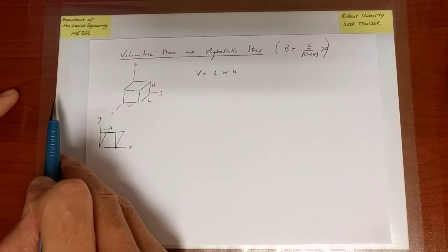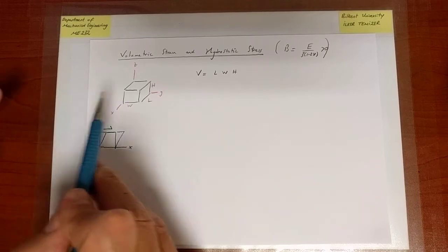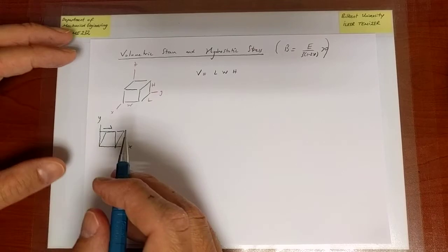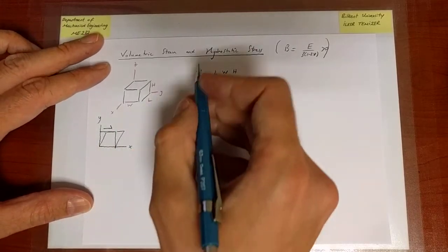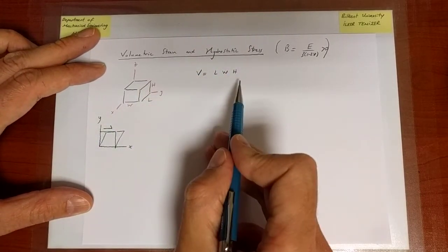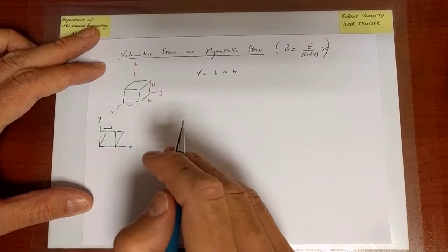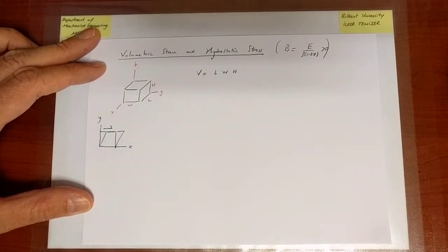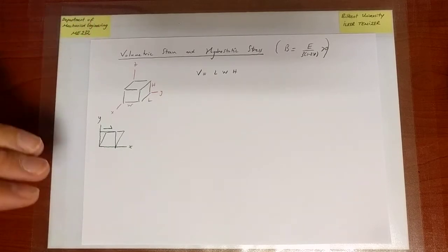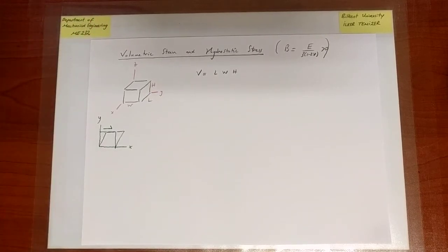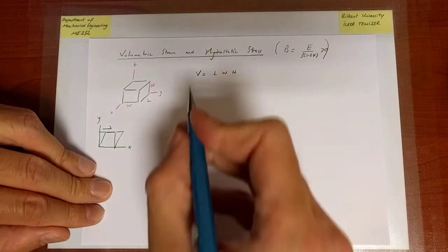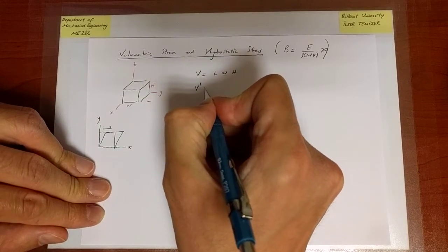But if the material is anisotropic, shear stresses can also cause normal strains and hence volume change. So ultimately it's true that volume change is only associated with normal strains, but only if the material is isotropic is volume change going to be induced by normal stresses alone. Having summarized that, and we're going to see the outcome of that summary in quantitative form shortly, let us now try to calculate the new volume of the block after deformation.